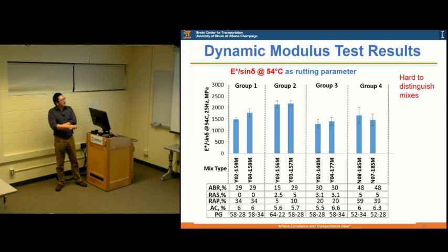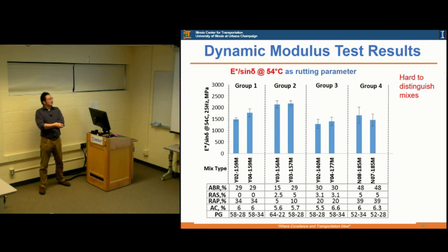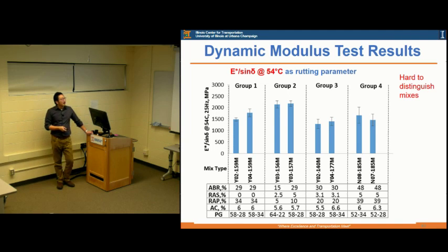But in this case, you can really see, for example, these three groups - they are very close, right? And also they get very high variation. So I would say it's very hard to just use E star over sine phase angle at 54 degrees to distinguish mixes in terms of rutting resistance.